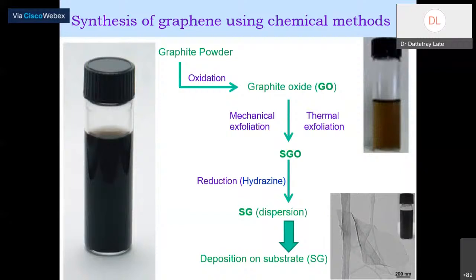Suppose graphene is synthesized by a very simple chemistry method. For example, you have graphite powder. You put this graphite powder in a strong acid such as H2SO4. You have oxidation, and once the oxidation is done, you will get graphite oxide. Then do mechanical exfoliation or thermal exfoliation, meaning you heat this graphite oxide at high temperature, and you will get single graphite oxide layers. Of course, we need to reduce it because it has a lot of functional groups. Hydrazine is a very good reducing agent. You can reduce this graphite oxide to get a single layer of graphene.